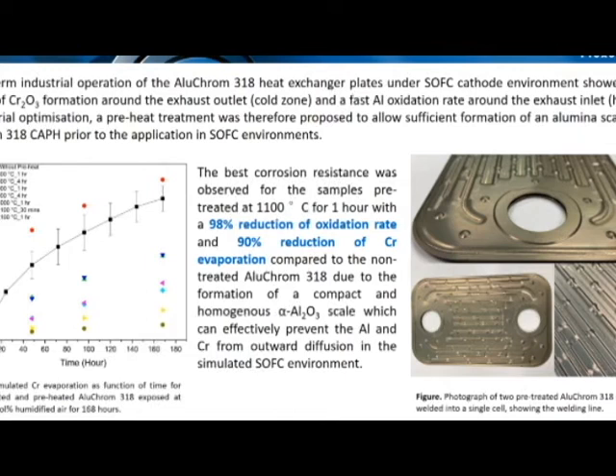Different temperatures will cause the formation of alumina with different phases. Like at 800 degrees, it will form metastable alumina like gamma alumina. 1100 degrees will form alpha alumina on the steel surface. Compared to the metastable alumina, alpha alumina has the best chromium retention ability.